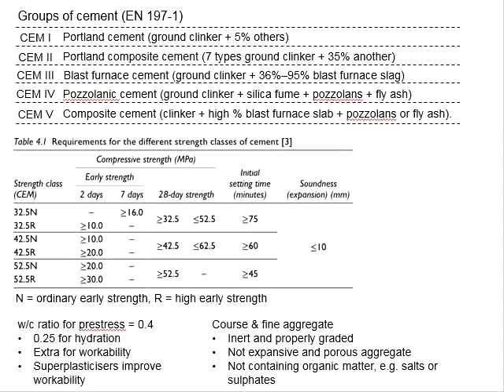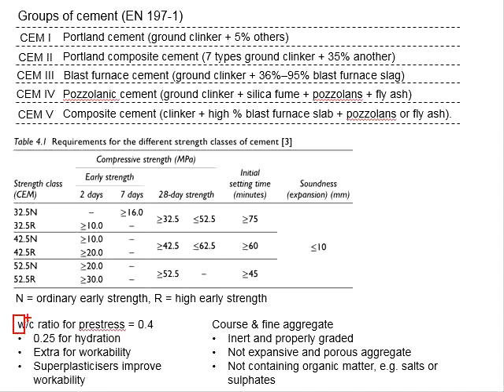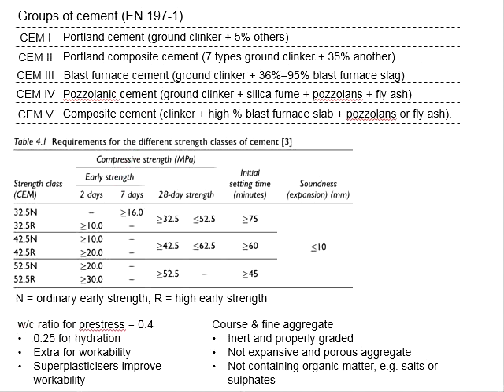For the typical concrete used in pre-stressed members, the typical water-cement ratio is about 0.4, meaning the weight of water over the weight of cement is 0.4. However, this 0.4 water-cement ratio is not fully utilized for the hydration process — only 0.25 is used for hydration.